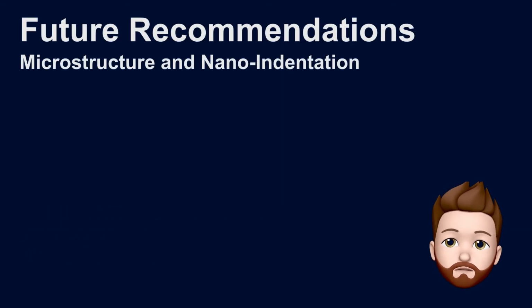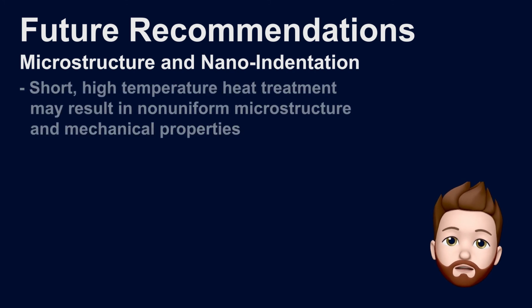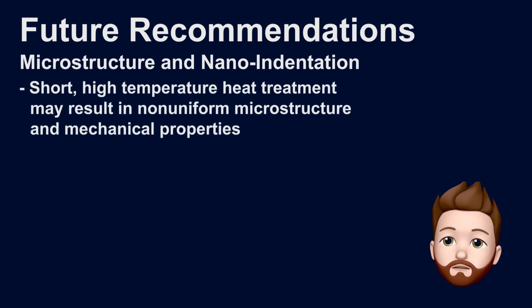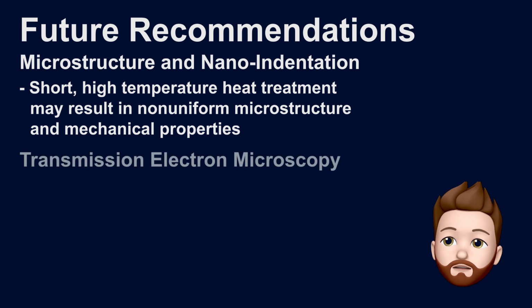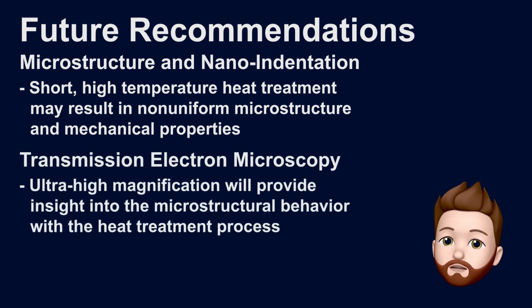Further experimentation is required to determine if the short time and high temperature results in any sort of hardness or microstructure gradient throughout the part, which could result in less ideal mechanical properties. This, in conjunction with slightly longer times and lower temperatures, could result in a more uniform treatment of parts of various shapes and sizes. In addition, TEM analysis of the samples to determine the effect of heat treatment on the microstructure of the material would provide significant insight.